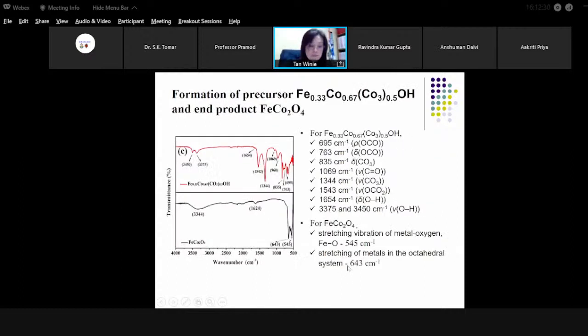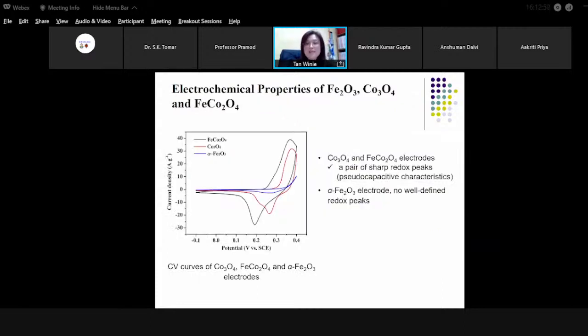So we do the same thing. These are the characteristic peaks as shown by the precursor. Okay, and again, the formation of the iron cobaltite is also manifested in the FTIR study with two distinct peaks at 545 and also 643. Okay, so we do electrochemical property studies for these three materials, the single oxides and also the mixed transition oxide.